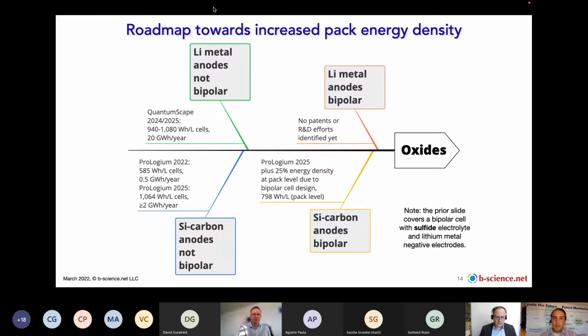And so, yeah, one can understand why different decisions are being made, because the risks are concentrated in different places. So with the bipolar cells, there is of course the risk if it doesn't work, then Prologium also does offer non-bipolar cells, then the energy density is a bit lower, but there is this opportunity to do it gradually, while with lithium metal that is basically 100% lithium metal. And then of course there's the question, is it possible to combine lithium metal anodes with bipolar cell architectures? That is a very big challenge because of the risk of lithium dendrite formation that can form short circuits.